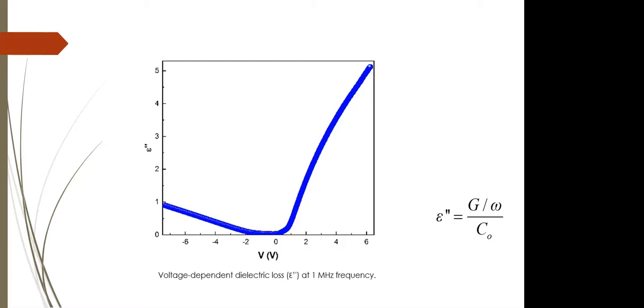Considering that the dielectric constant is calculated from the capacitance value and dielectric loss is calculated from the conductance values, the relationship between dielectric constant and dielectric loss is expected to behave similarly to the relationship between capacitance and conductance. Our results show us that also. In the literature, low or negative dielectric constant values in the accumulation region and the high dielectric loss values are attributed to the addition to the internal impedance of the device.